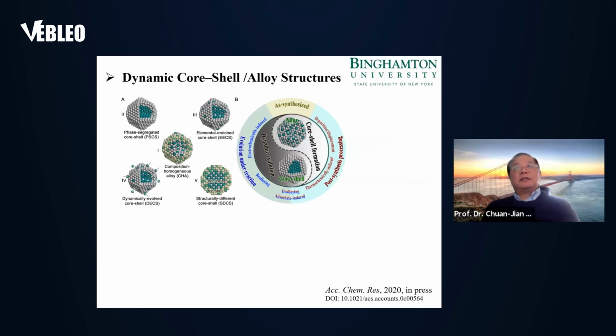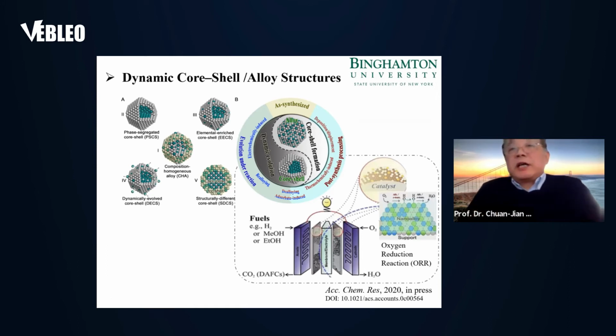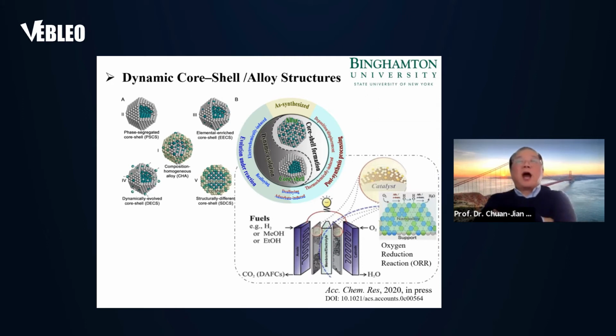Now, the next part is we want to illustrate a fuel cell reaction. So in the fuel cell reaction, we want to illustrate the surface site is also highly dynamic. As illustrated in this particular slide, if we prepare a nanoparticle, a nanoalloy structure in the middle, then during the reaction, we can have a different kind of phase segregated core shell structure, a dynamically evolved core shell structure, or structurally different core shell structure, etc. In order to understand this, we load the catalyst in a fuel cell. Then we examine the catalyst change as a function of time during the operation of the fuel cell reaction. Okay, particular emphasis is placed on the oxygen reduction reaction as illustrated here.